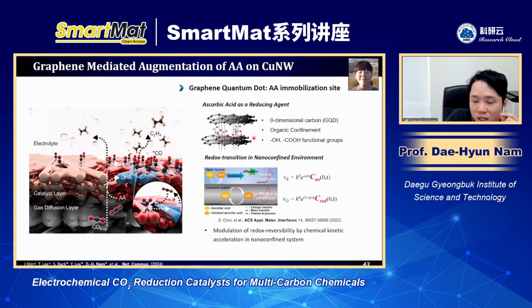And this is also very important because for the continuous redox cycle, the electron should be supplied from the electrode. In this way, this ascorbic acid should be confined in the carbon-based supporter. And this kind of redox transition has also been reported recently in another paper. And we try to apply this kind of principle to our catalyst.